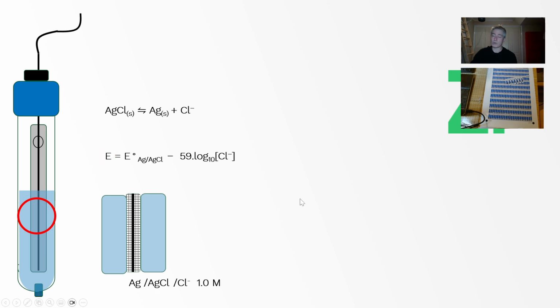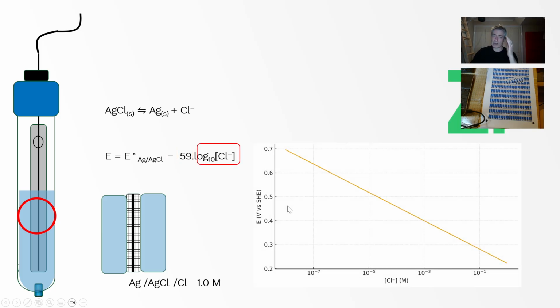Now, I chose 1 molar because it's simple enough that the log of 1 is 0. So what does that mean then? It means that the reference potential of a true silver chloride reference electrode is actually dependent on the chloride concentration that you have within the reference electrode. So when it's 1 molar, we'll have a standard potential, as I say, of about 0.22 volts.